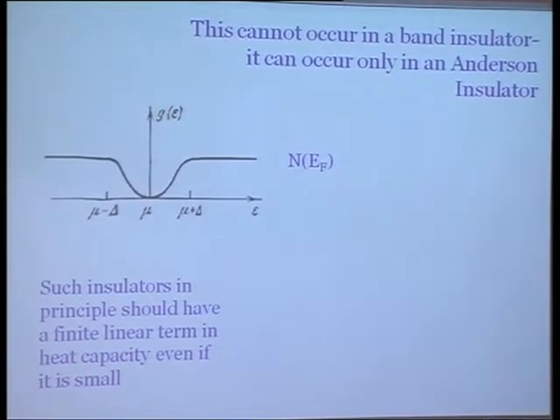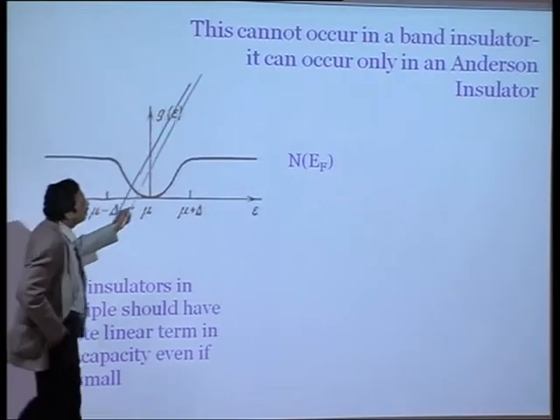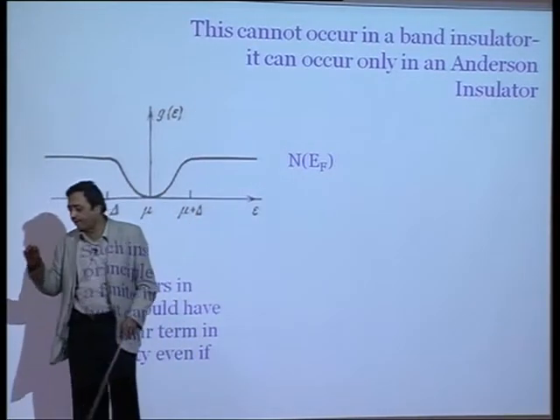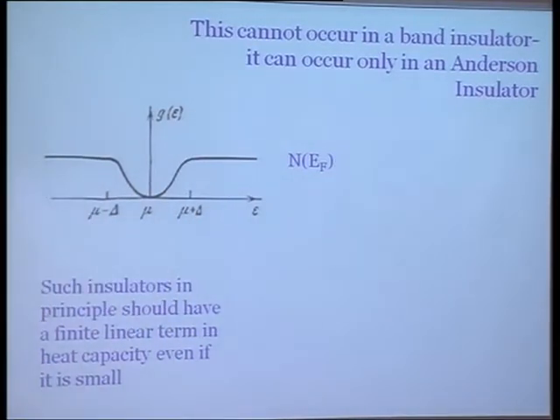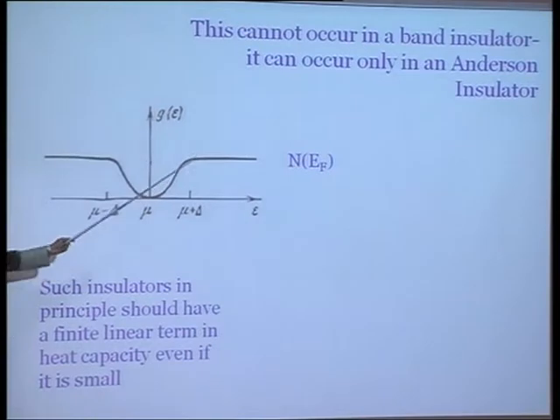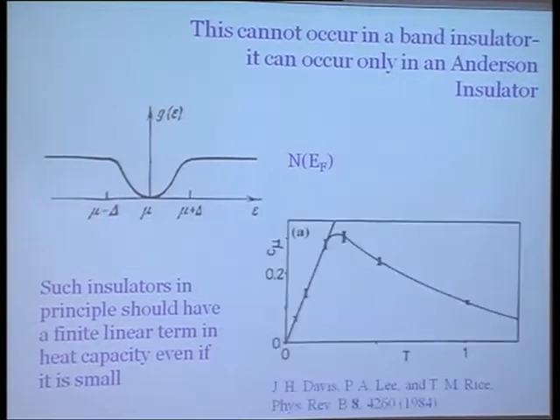There's one thing I would like to remind you: when you say that, you are not actually talking of a band insulator. You are really talking of an Anderson insulator, because you need a finite density of states here. You are digging a hole into the finite density of states. If you have a band insulator with no density of states, you are not going to get this particular type of effect. So such insulators in principle should have a finite linear term in heat capacity, even if it is small.